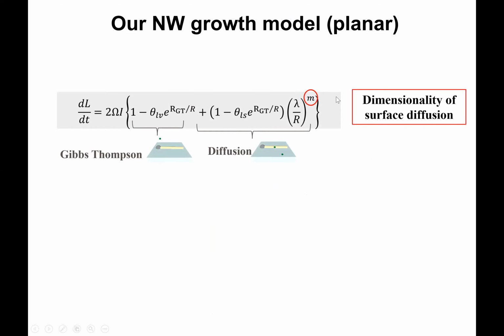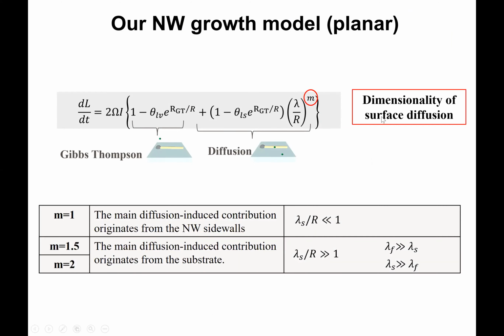And what was interesting is that the diffusion part had a power exponent that represented the dimensionality of the surface diffusion. Namely, if the diffusion is predominantly along the wire, this dimensionality is 1, like the 1 dimension of the nanowire. But if it is on the surface, then it should be between 1.5 and 2.